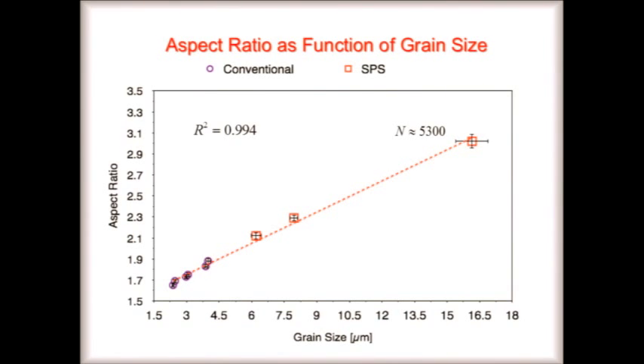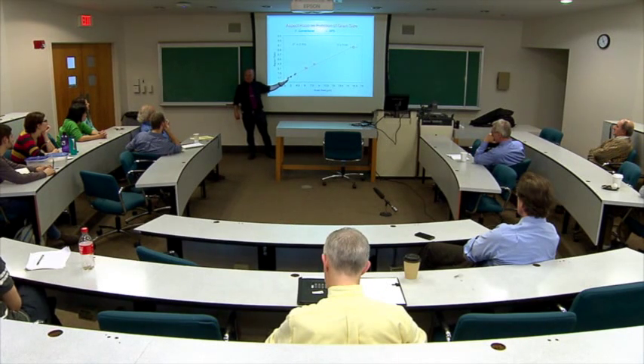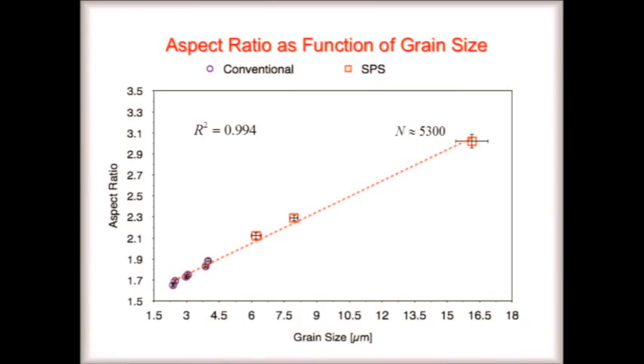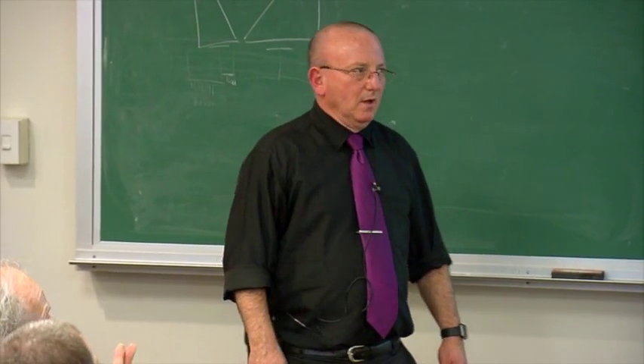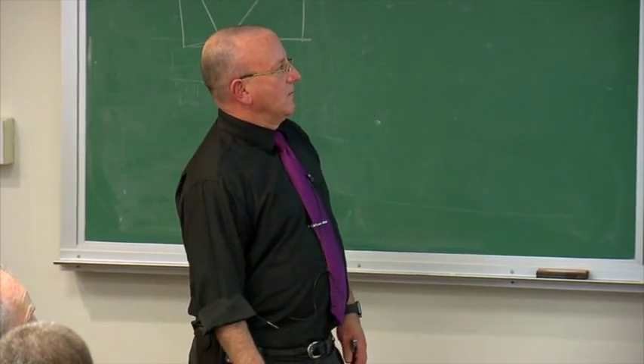Ignore the SPS for a moment. One can imagine that we have an aspect ratio which is evolving, but at some point it's got to taper off. And we've got to reach an equilibrium, not an equilibrium crystal shape, a kinetic crystal shape, and an aspect ratio that should more or less asymptotically die off. I think what's happened here is that with the SPS, we've just gone through that, and hopefully at some point, which we didn't get to, that would happen up here. That's the only explanation I have for this graph. Curious to see if you guys have other thoughts.